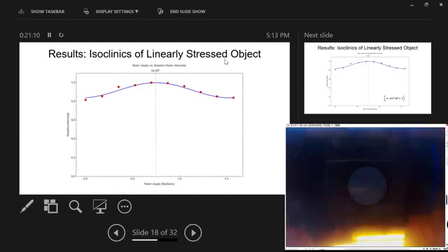This is the data we took that corresponds to our 10-degree increments, the relative intensity of our full field of view of the polariscope. The dots correspond to the data we took, using what I would call the image intensity. This isn't a real intensity taken with an intensity meter. It's just the average gray value of the image, which we got using ImageJ. So it's a pseudo intensity measurement, but it gets at the relative intensity of these images as we go through the 90-degree rotation.